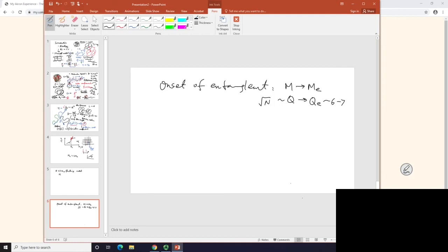So the power is not just this concept, but rather the bold assumption that all polymers, all linear flexible polymers, will start to get equally entangled, or start to feel crowded, at the same magic number of 6 or 7, universal.